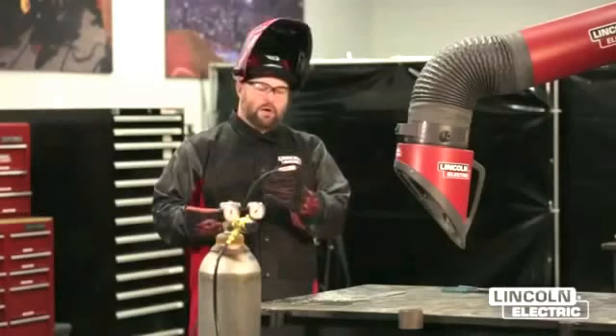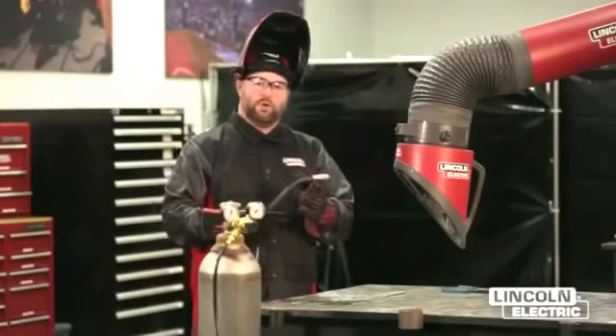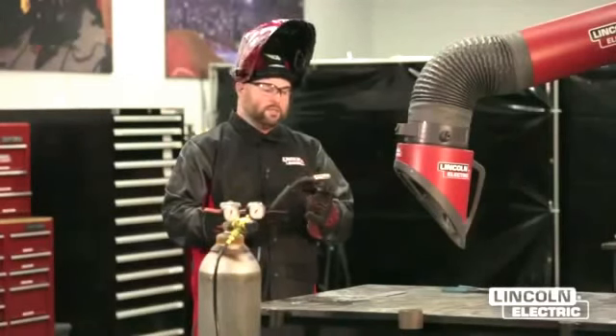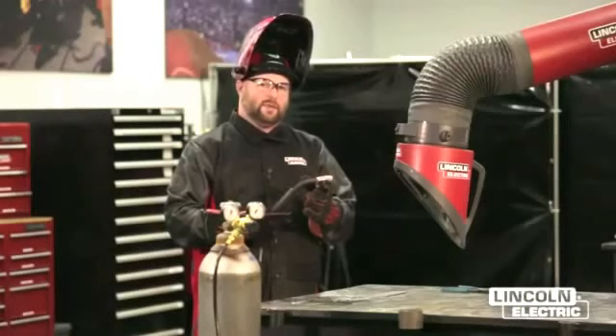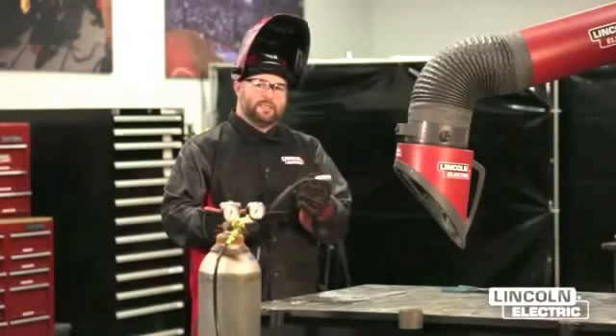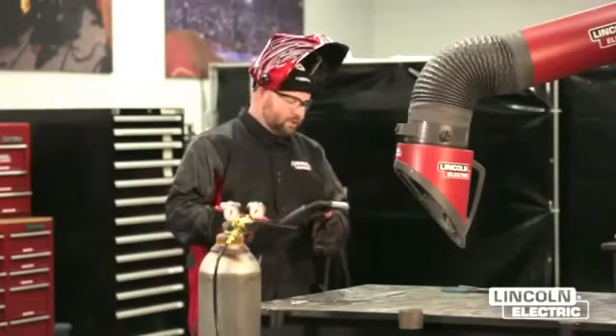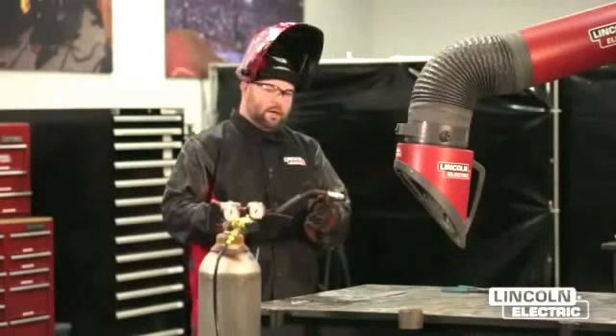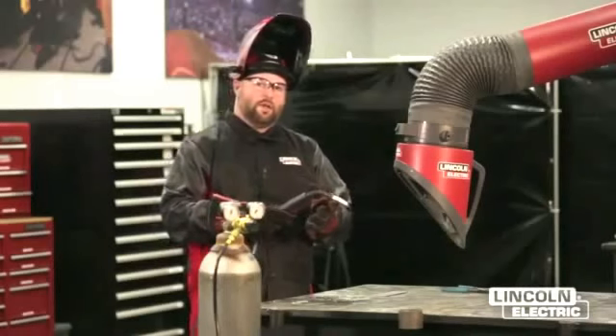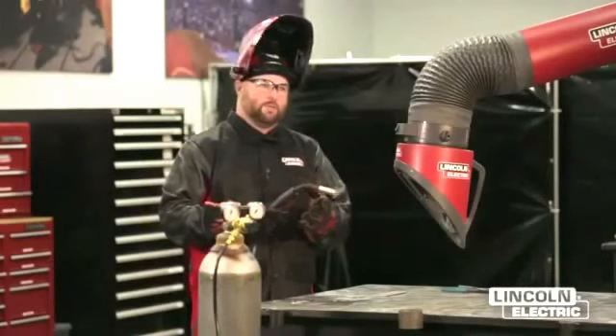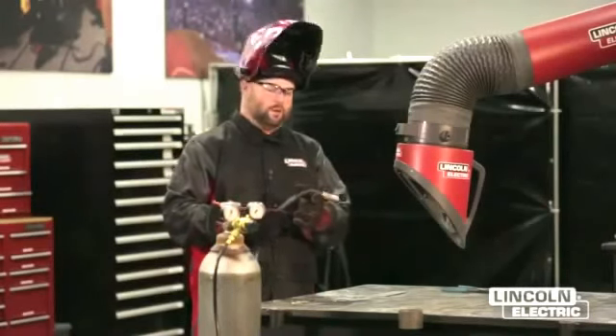With the short arc MIG process, you're looking for a fairly short contact tip to work distance. We've got it set here to about 3/8 of an inch. If you can maintain 3/8 of an inch, that's a good starting point for your MIG setup. So what I'm going to do is go further out and make a long contact tip to work distance, and we're going to see what happens to our weld.